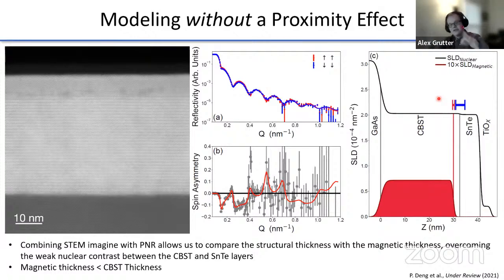So a little angle change or curvature might change the overall shape of the reflected beam, but it should be okay. If you are getting inhomogeneity that the neutron can detect, it will appear as an increase in the surface roughness. That is something that we do see a lot in van der Waals type materials like topological insulators, because they tend to form these nanometer sized terraces on the surface. And so locally you get really, really smooth looking interfaces in the TEM.